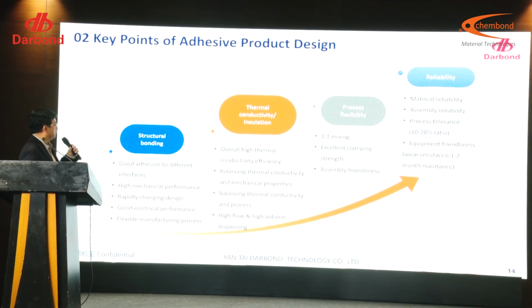So secondly, balancing thermal conductivity and mechanical property. Sometimes with this kind of adhesive, if you consider thermal conductivity, you put a lot of conductive filler in, you will sacrifice some mechanical property. So that's some challenge, some balancing you have to do. And balancing the thermal conductivity and the process. Again, if you put a lot of filler into the material, you probably will affect the viscosity and the flow property, which will affect the process.